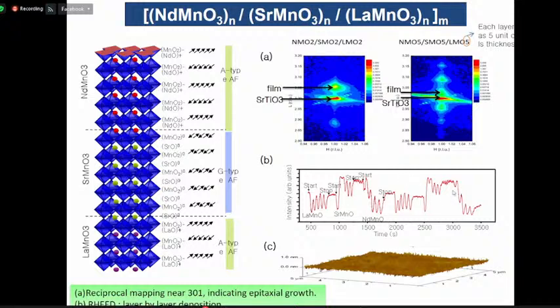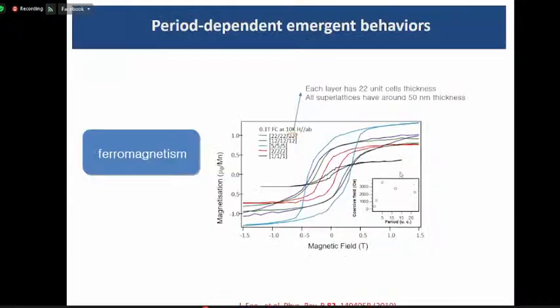Then let's move to the results. They show one layer and one layer texture. Okay, first, this antiferromagnetic insulator superlattice shows ferromagnetism. This is magnetic hysteresis. Depending on the thickness of each layer, they show different shapes of hysteresis.